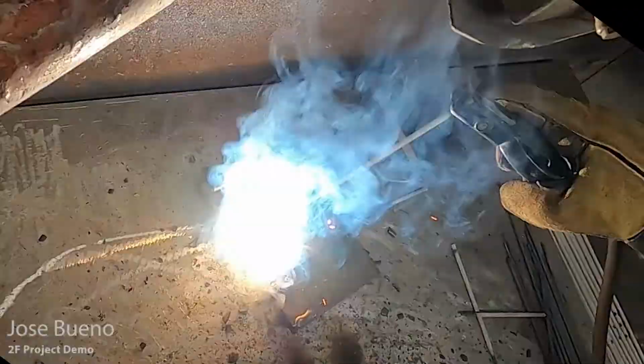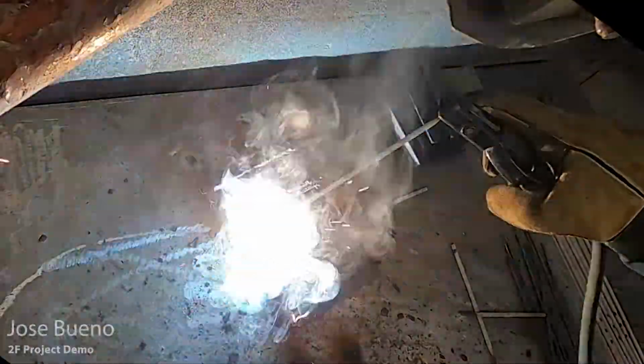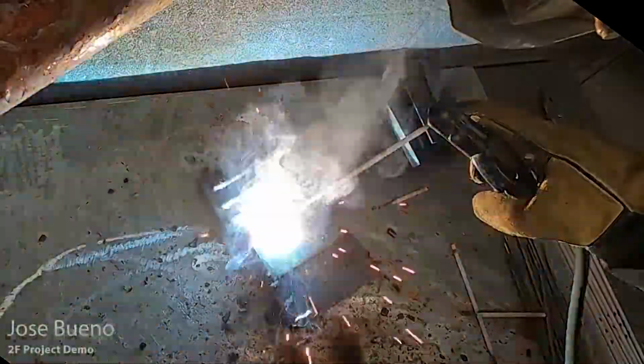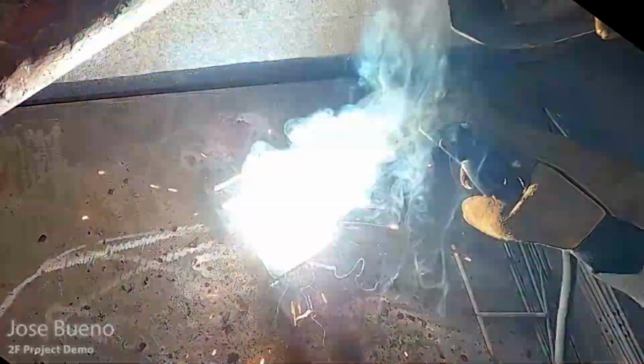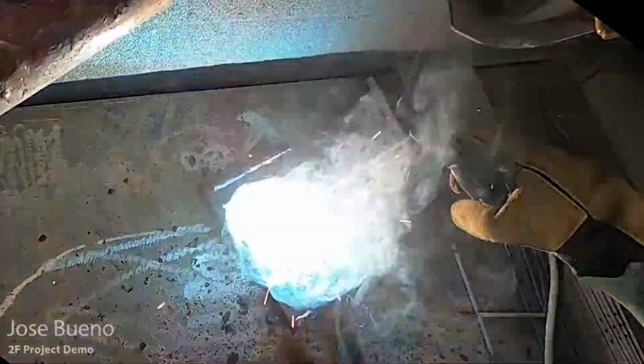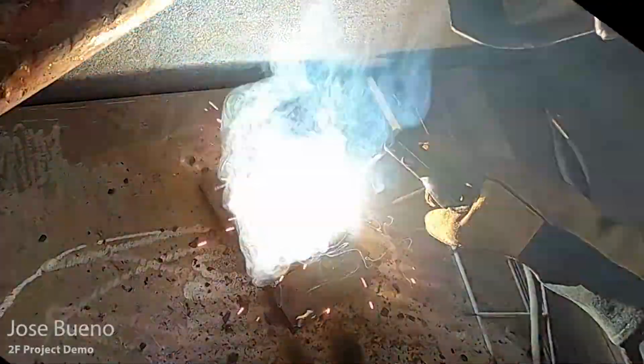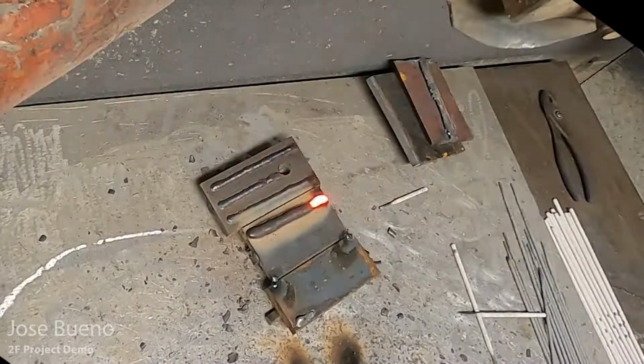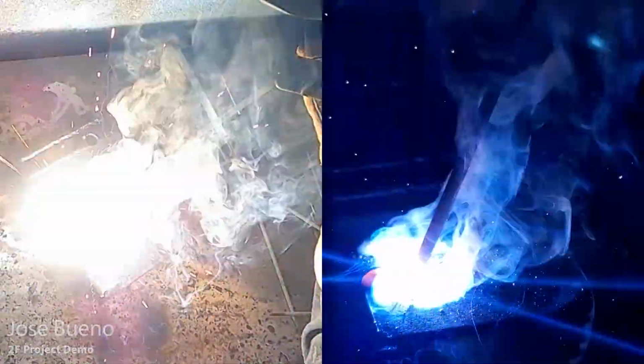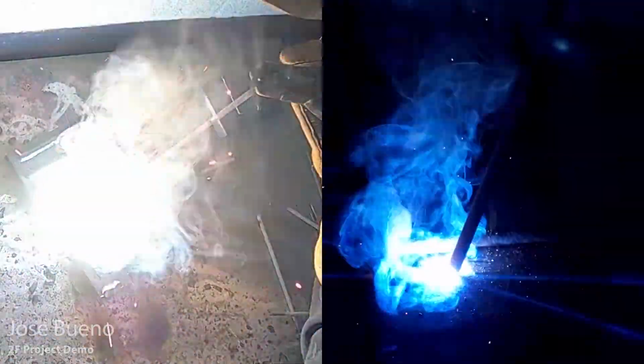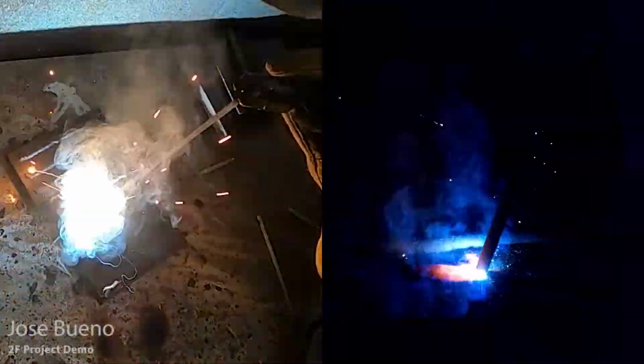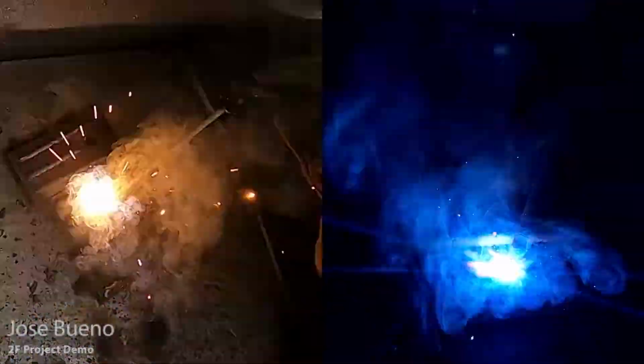And here I'm just running 3 more stringer beads with 7018. I upped my amperage to about 140 from 130, and the material that I'm welding is 1/2 inch steel plate. These plates were left out overnight and during the early morning, so they're pretty cold. I didn't apply any preheat. Those first 3 welds were a little rough in my opinion, so I'm hoping that with the addition of a few extra amps, I'm able to lay down some better welds. So we'll see.